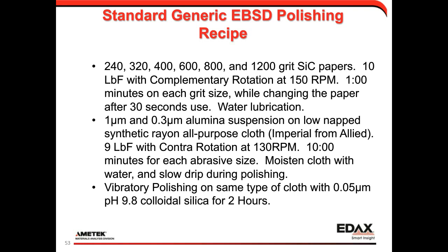In these cases, I moisten the cloth with water, and then I go to a slow drip just to keep it cool and clean, but not remove the abrasive. I periodically refresh the abrasive 2 or 3 times in that 10-minute span. And then I'll go to a vibratory polisher using the colloidal silica, generally for around 2 hours. If you don't have a vibratory polisher, you certainly can replicate this just using a wheel and a sample. You just have to keep solution on there for that sort of time, so you can drip it on. The vibratory polisher is nice because you just put the sample in a tray with the cloth and the solution, and it just keeps moving with a little sample weight until you take it off.